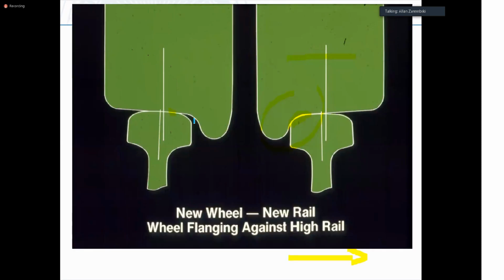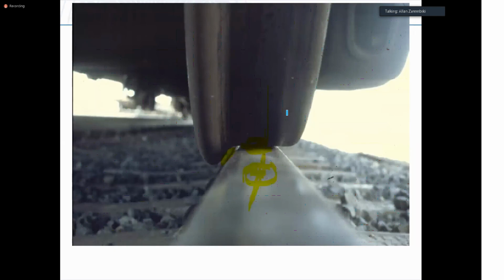The problem is you can't get this on a sharp curve. This is impossible on a sharp curve, because in a sharp curve, you're going to flange. Even on a medium. So we're talking now about curves only. Medium to sharp curves, exactly. So in straight track, you should be doing this. This is what it should look like on straight track, and you should not have a problem with one-point contact. The contact should always be over here.